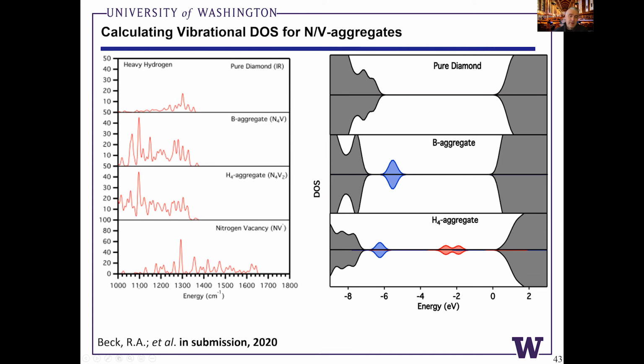And there's some clear differences, particularly at lower phonon frequencies, around 1100 wave numbers. There's some spikes in the VDOS. This is an H4 aggregate, which is slightly different than the B aggregate, this N4V complex. But one thing we'd like to do is use low loss EELS to do vibrational spectroscopy, aloof EELS measurements. And we might be able to see this vibrational signature of the B center using low loss EELS spectra. And these calculations will help guide those measurements.